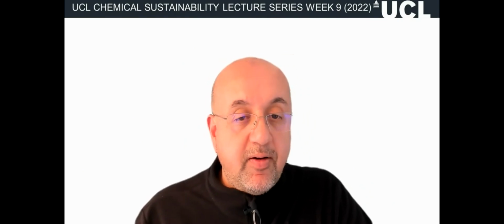So first thing is that there was some literature background saying zirconia doping can improve. First thing is NMC811 is notoriously unstable in terms of, if you leave it lying around, it goes off. Everybody's interested in it because of high nickel, but they know that you need to do something with it. So generally what people are doing is they're coating the surface to protect it with something that will be more stable. And usually it's a lithium-ion conductor.